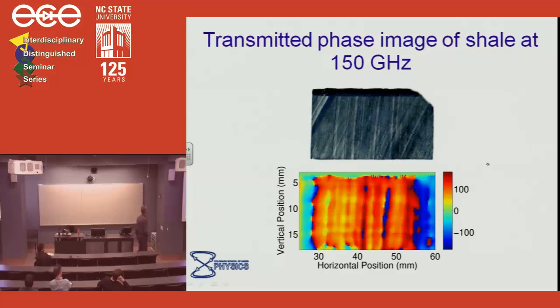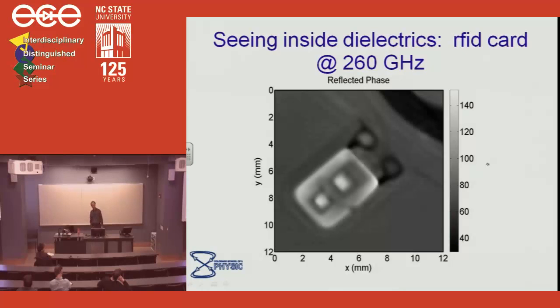And so this turned out to be quite a surprise to them that we could estimate the organic content of their samples so easily. Go up to higher frequency. All of us probably have these RFID cards that get you in various buildings. The nice thing about the millimeter waves is they see right through dielectric. So this is the actual RFID chip inside my CSM ID card. You can't see it that well on this projection, but we're getting resolution well under 100 microns. And I think we could do much better than that if there were any interest in that. So you can see right through dielectrics, which is one of the real advantages of millimeter waves.